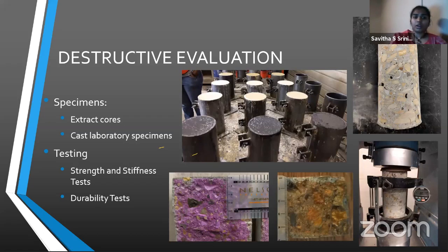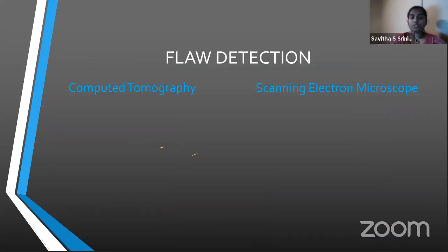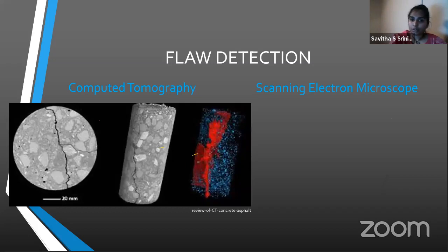So you can also do flaw detection. That is, you can see if there are any flaws in your specimens using things like computer tomography, which essentially uses X-rays to digitally cut a specimen open to reveal what's inside. So what you can see here in this picture is a cracked specimen, and the red portions indicate where the crack exactly is in the specimen.